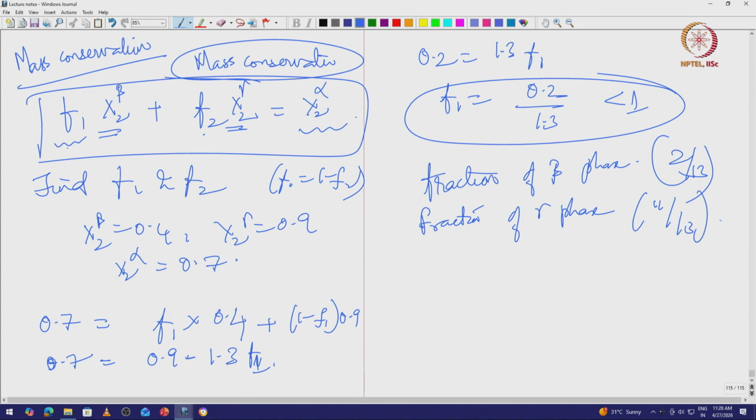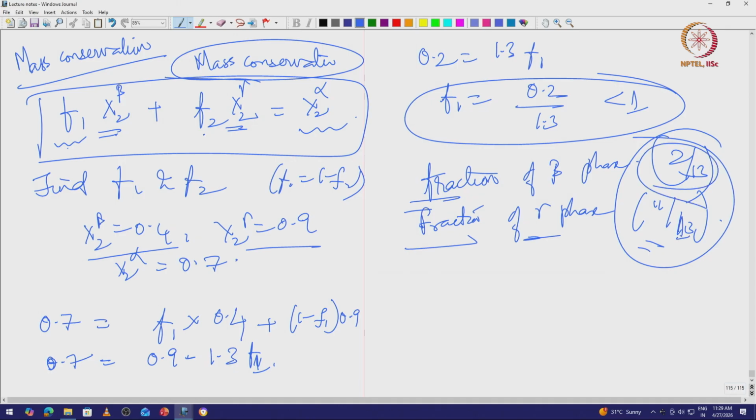So, that is how you do solute partition, but once you do that and you know that the compositions in each of these phases is so and so, that also determines the fraction of these phases. So the total amount of solid that has converted to gamma will be 4/13th, the total amount of solid that has converted to beta will be 2/13th. So, that is how you can estimate the fractions.